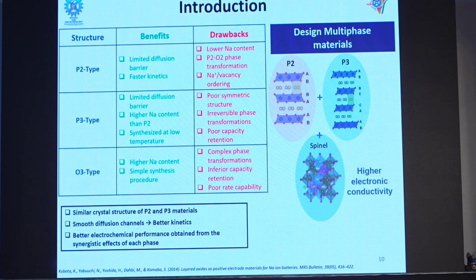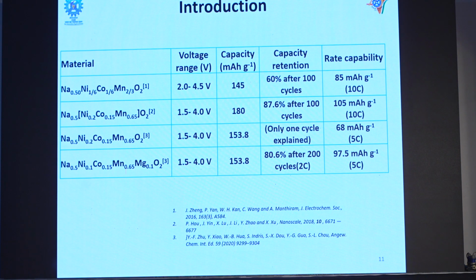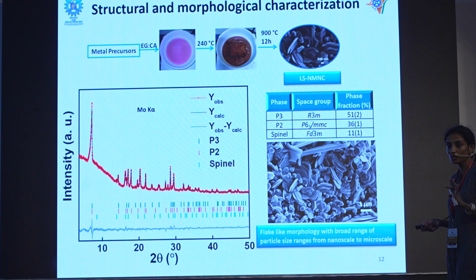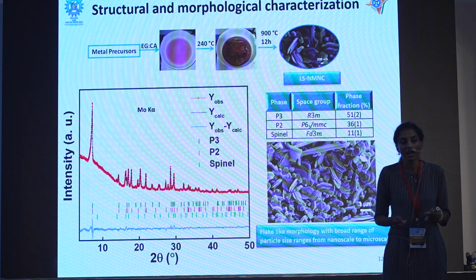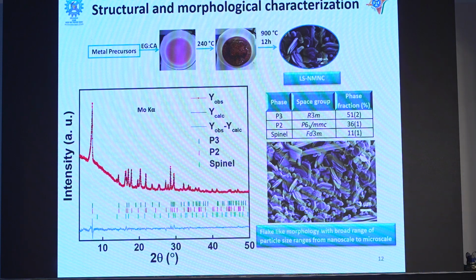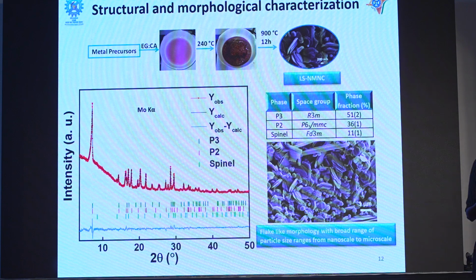Higher electronic conductivity will increase the rate capability, that is the sodium transport will be accelerated and we can end up with a higher power density in our battery. So this is the composition of the material we have synthesized. And we have also investigated the literature. There are only 4 P2, P3 spinel structures reported in the literature, but nobody has bothered to understand why it improves. There is a suggestion that electronic conductivity is improving it, but what happens to the spinel phase during cycling? What happens to the layered phases during cycling? Is it completely reversible, irreversible? There were so many open questions, and these are the questions we try to address in this particular work.